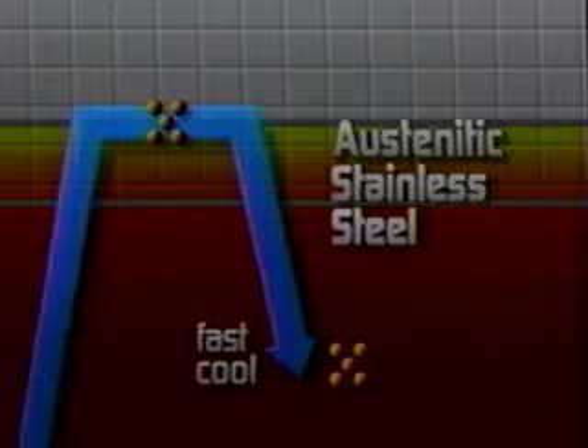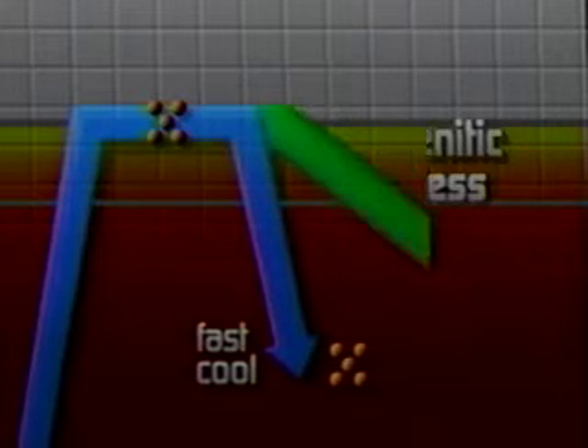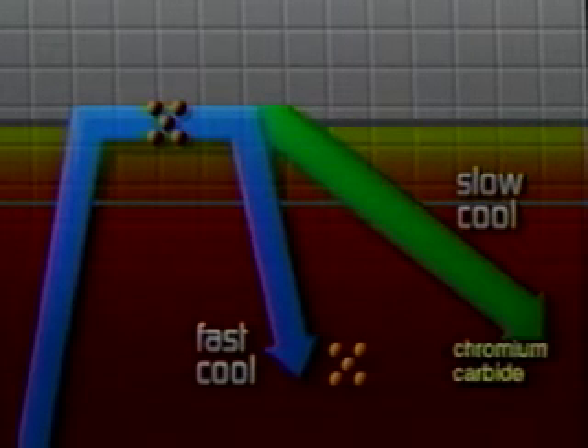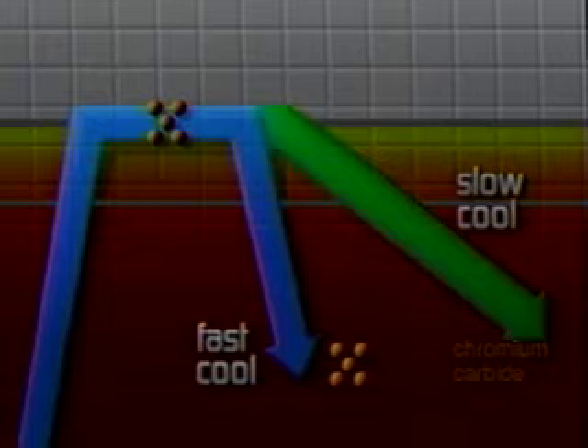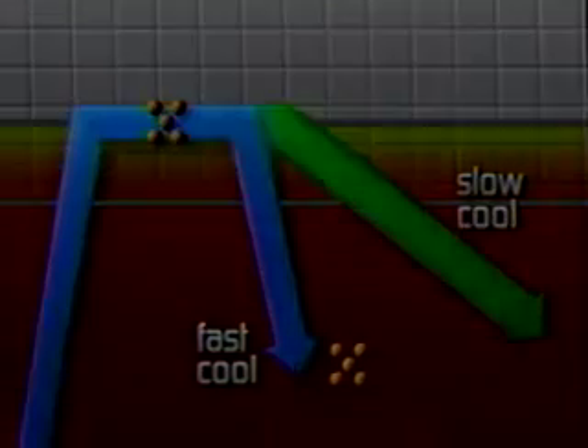Quenching prevents the formation of chromium carbide and retains the chromium atoms in solid solution. Therefore, the corrosion resistance of the austenitic stainless steel remains undiminished.